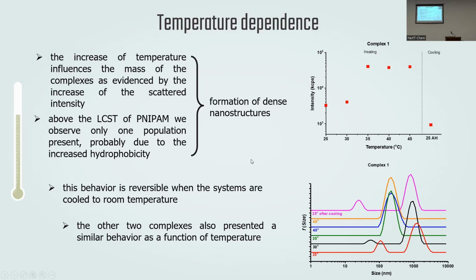Also, from the size distributions, we can see that above the LCST of PNIPAM, we observe only one population. This is most probably due to the increased hydrophobicity of the synthetic polymer. These results suggest the formation of dense nanostructures. Also, this behavior is reversible when the systems are cooled to room temperature. Here is presented only complex 1, but the other 2 complexes present similar behavior as a function of temperature, which is also the behavior of the PNIPAM.